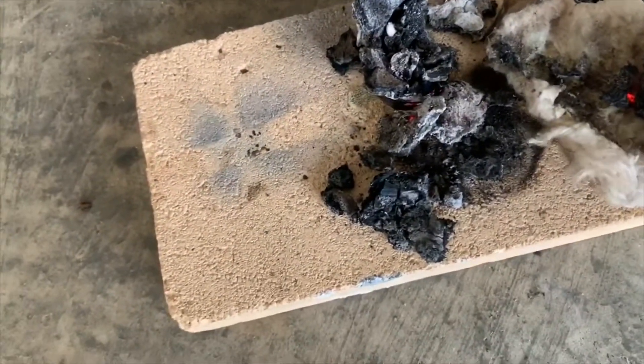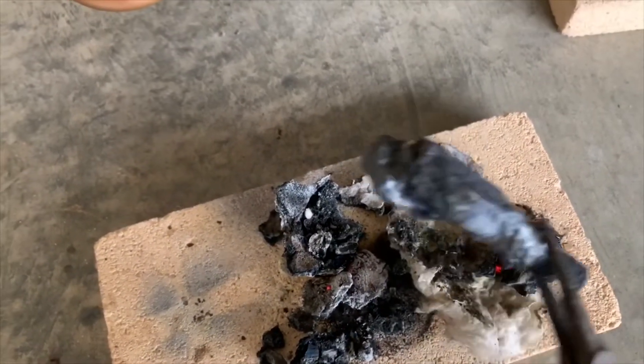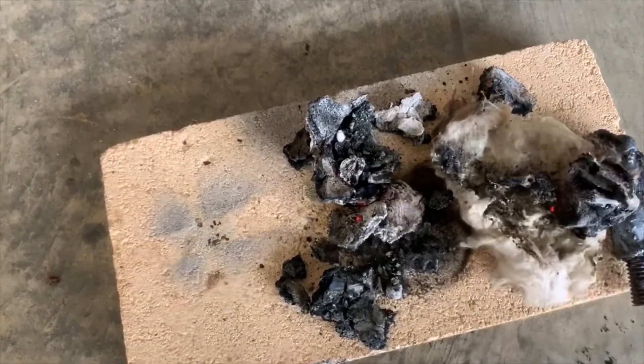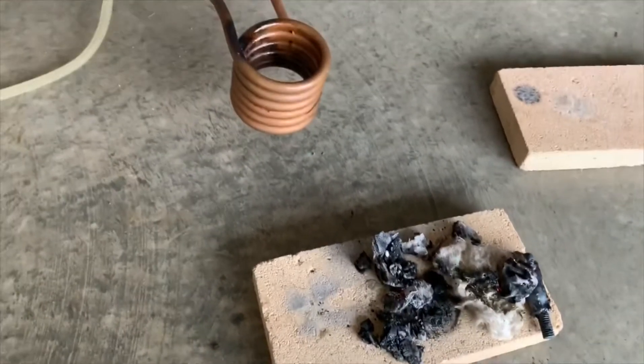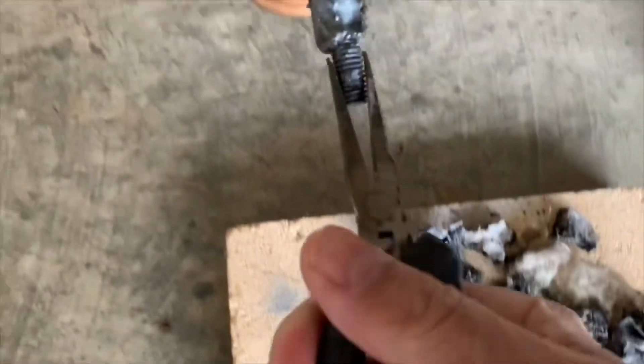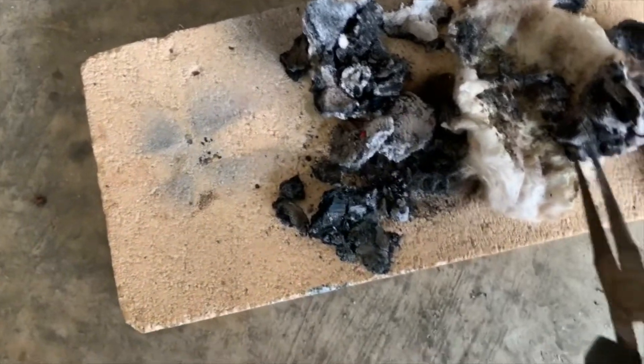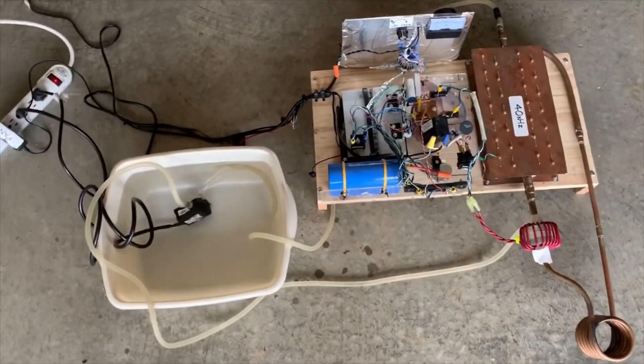So anyway folks, this is what's left of our crucible - not a whole lot. Here's a piece of melted iron, all deformed, with some smoking carbon still remaining in this mass. The assessment overall is that in terms of induction heaters, you could probably get a one-time use out of the crucible. The metal shorted out against the turns of the induction heater, so all in all, not that useful - but thought you'd find that interesting. Please do check back for more videos and please don't forget to subscribe.